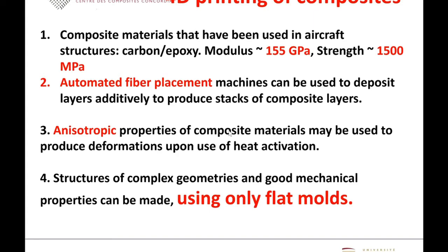The third difference is that rather than having the different materials at different positions along the stack of the deposition, we depend upon the anisotropic properties. That means the change of the different properties along the different directions of the materials gives rise to the interaction between the layers, and that kind of anisotropic property gives rise to the change in the shape of the material. So by using this, we would be able to make structures of complex geometry with good mechanical properties using only flat molds.